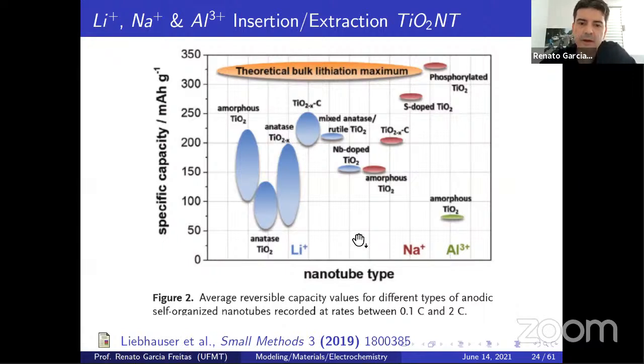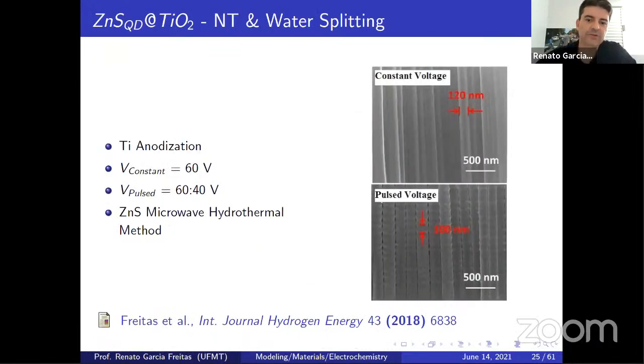So it's a very common template for battery energy storage conversion, and for energy conversion for solar cells and water splitting as well. So in this paper, we studied the effect of inserting a defect, because as we know, as soon as we have a photon with energy higher than the band gap, we have the exciton formation, we have electron hole diffusion, and we have the recombination of electron hole. But for sure, we can consider it as a ballistic conduction, but if we insert defects purposely, intentionally,